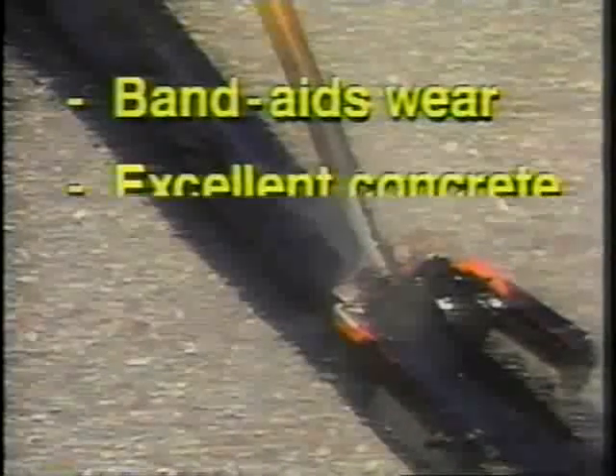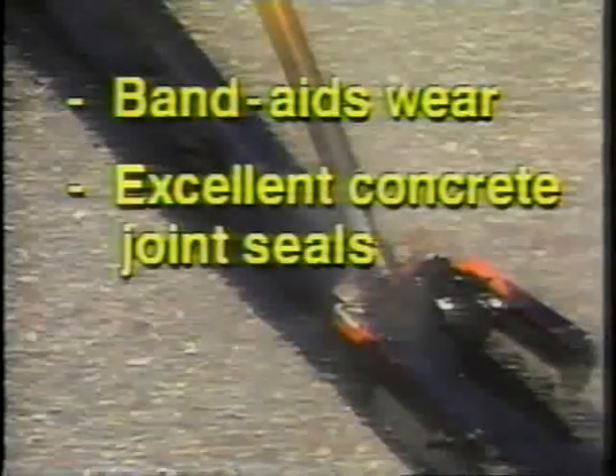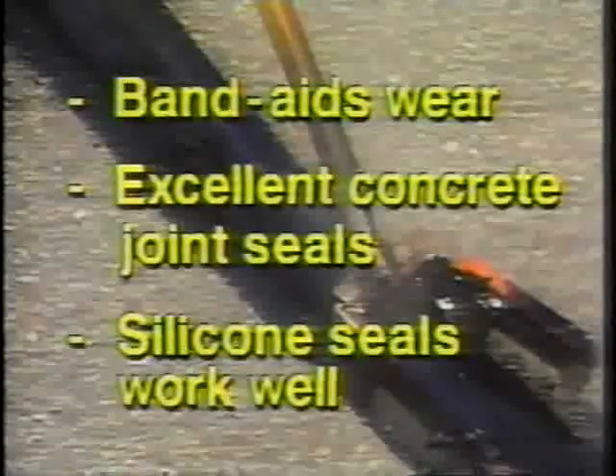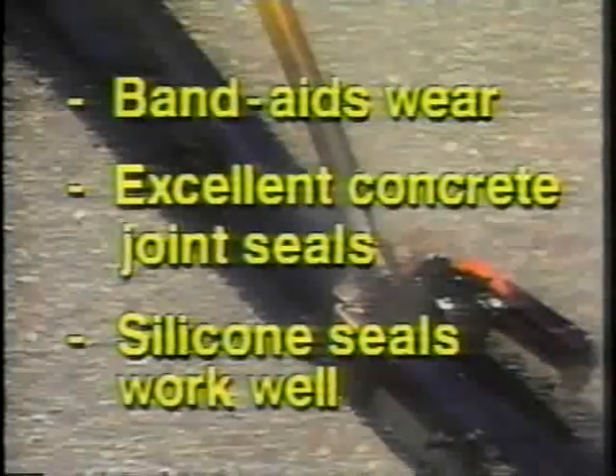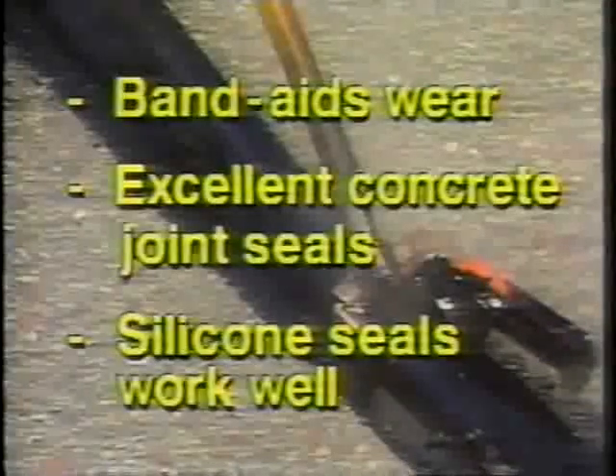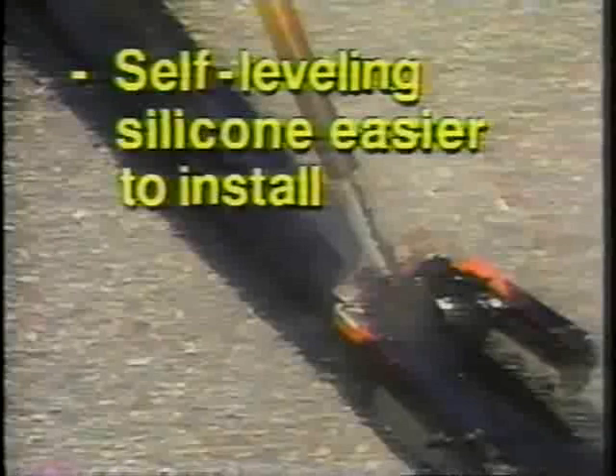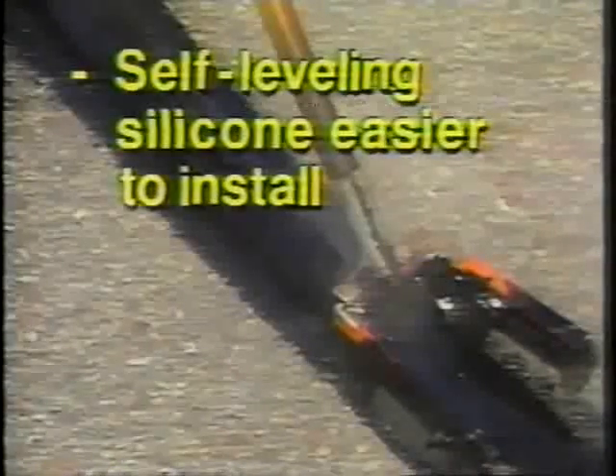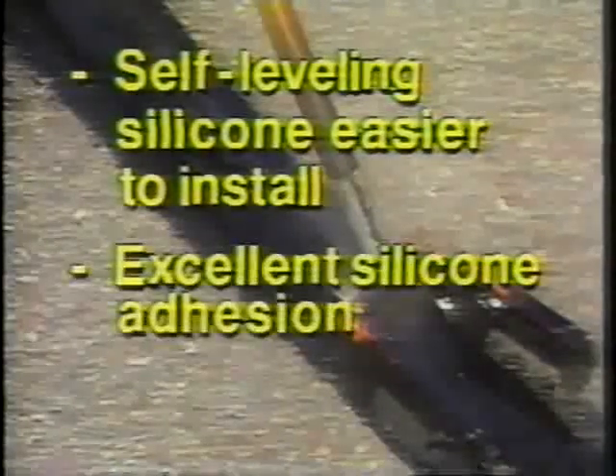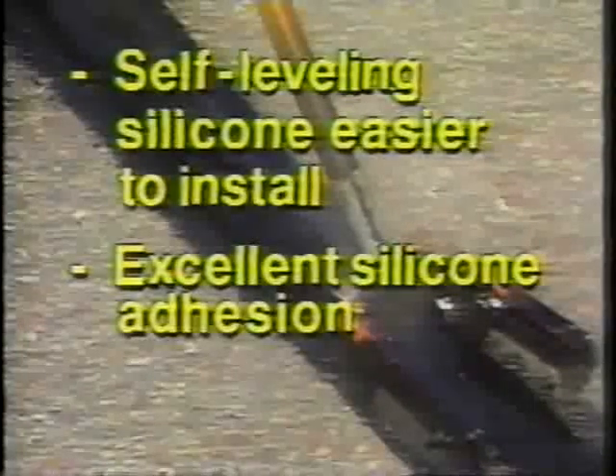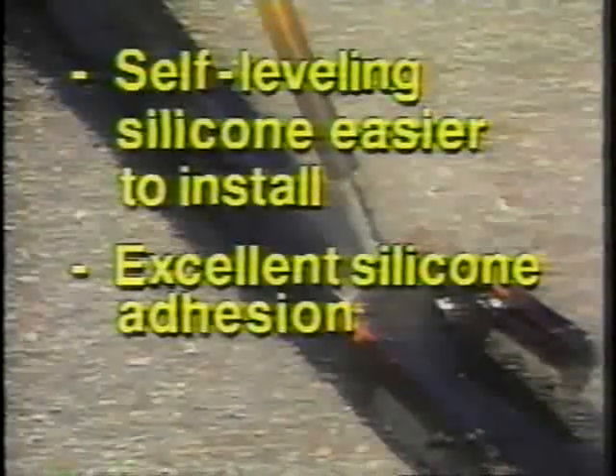We can also make some early performance observations. Asphalt Band-Aids used in this research showed early wear from traffic. Virtually none of the concrete joint seals have failed. Silicone sealants work well if the backer rod is installed properly and the sealant is kept clean prior to setting. Self-leveling silicone sealants are easier to install. All silicones are exhibiting excellent adhesion characteristics and outstanding resistance to intrusion.